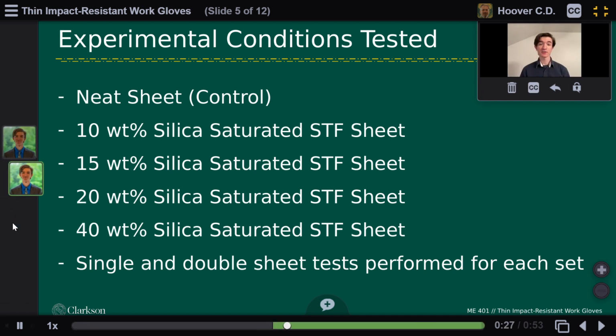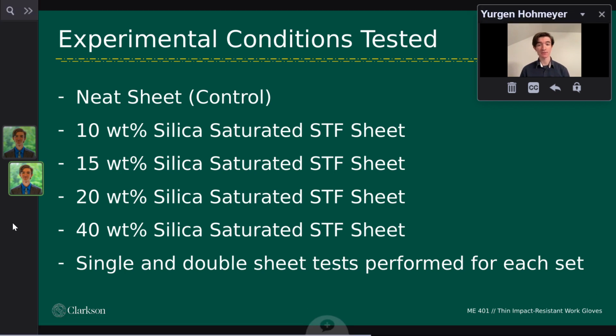The experimental conditions tested were varying levels of silica by percent weight in the STF mixture, which was then used to saturate the Kevlar sheets. Tests were conducted for neat sheets, our control sample, as well as 10, 15, 20, and 40% weight silica STF saturated sheets. For each set, 3 trials were performed using a single sheet and 3 trials were performed using 2 layers of Kevlar sheets.